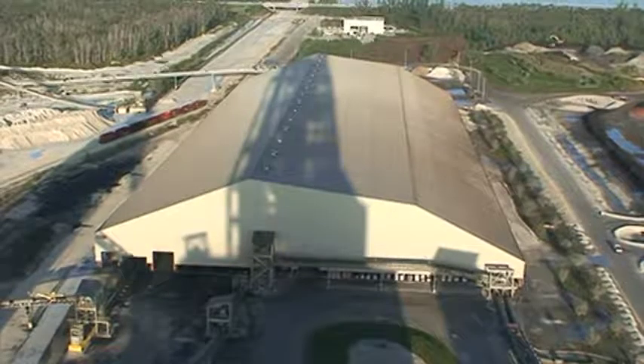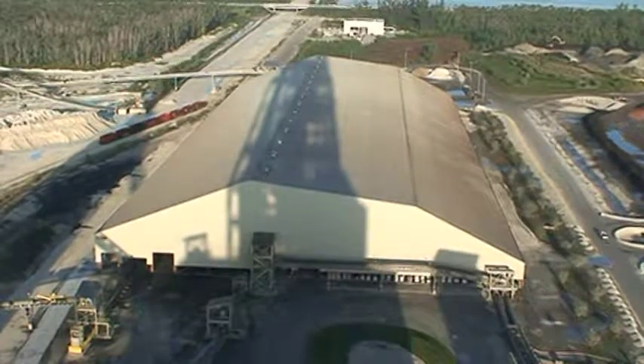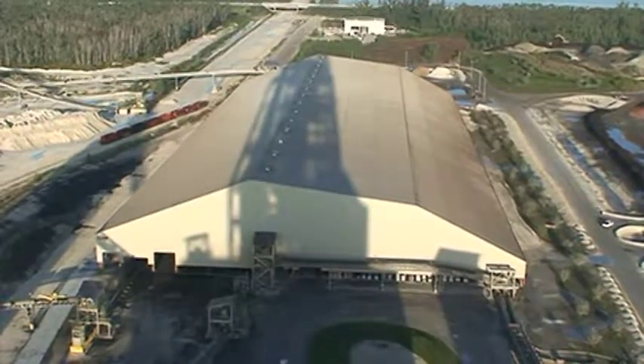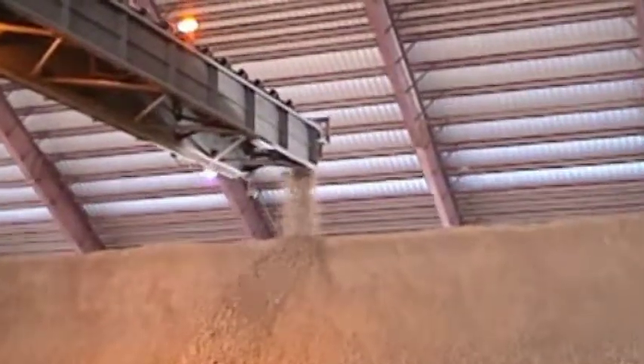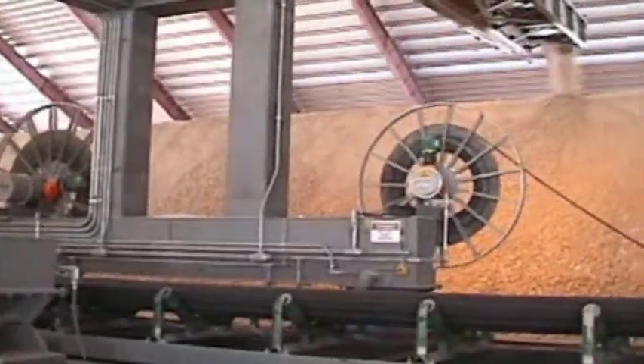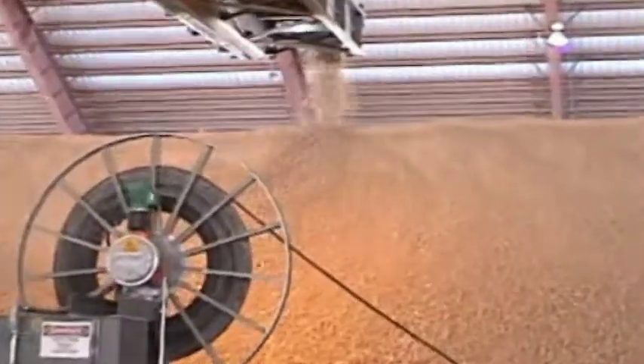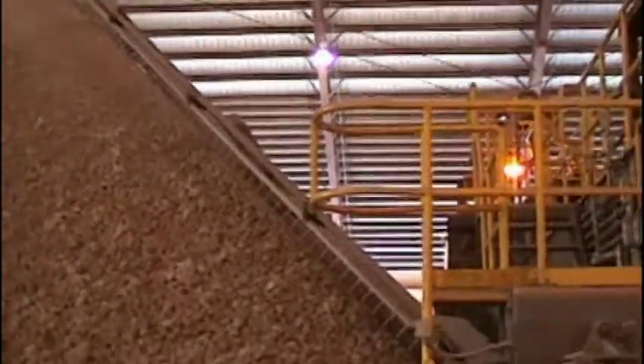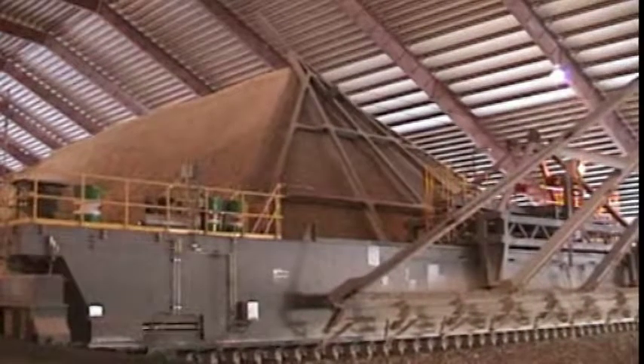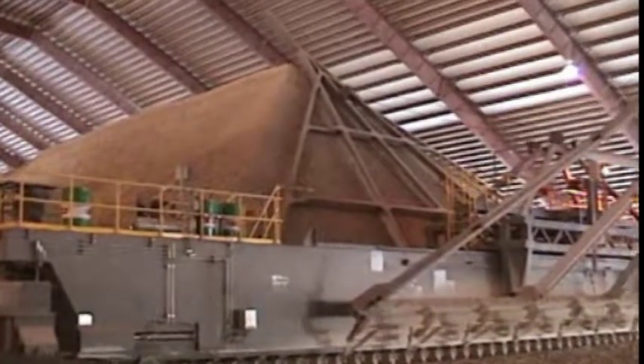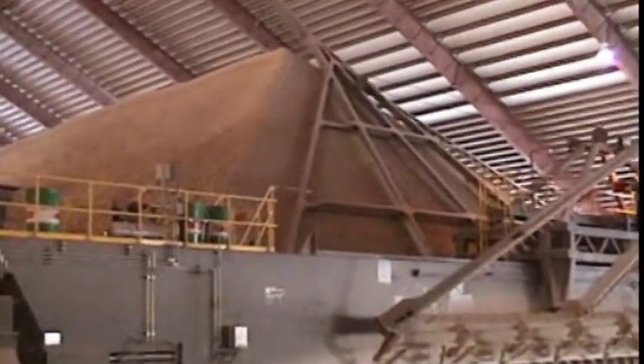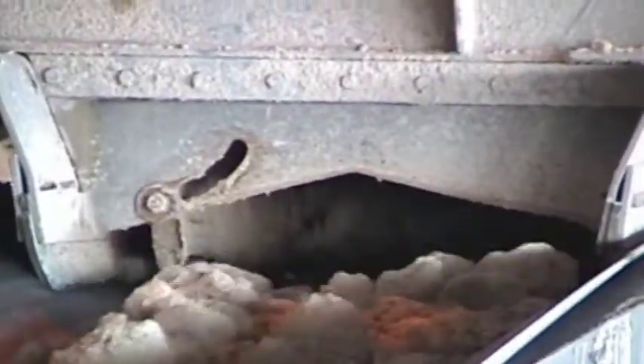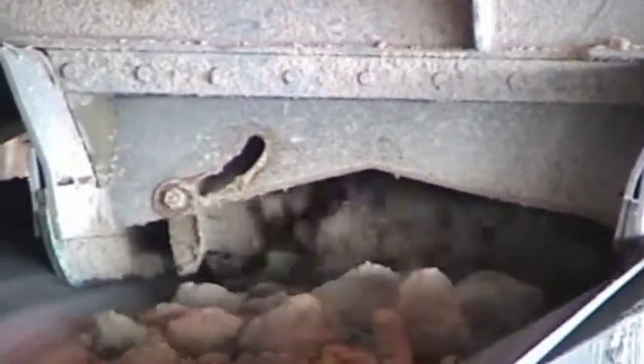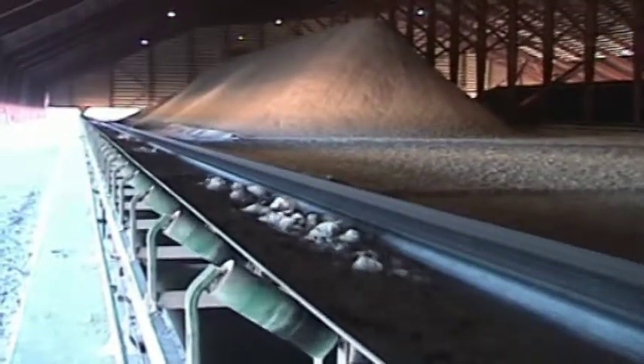The material storage building, a 400,000 square foot storage facility, houses blended stone, additives, and coal. The FLS LHO homogenizing store is designed for longitudinal stacking according to the chevron method. With 2 stockpiles in line, stacking takes place in one pile as the other is reclaimed. When reclaiming blended stone, a raking harrow system mounted on the bridge uses a sweeping motion to bring material down to a scraper that collects and delivers it onto a conveyor at a rate of 600 tons an hour.